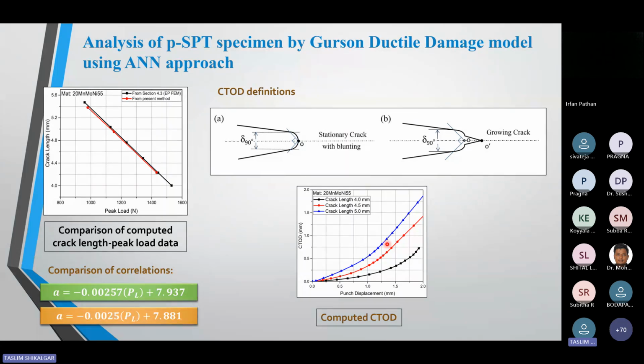All researchers decided to calculate CTOD at the fixed initial crack. If the crack is growing, they still do not change the crack tip location. So I used this methodology to calculate the CTOD for the growing crack. And here you can see this.